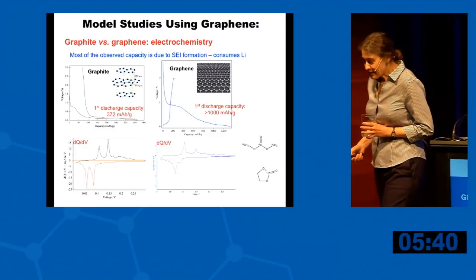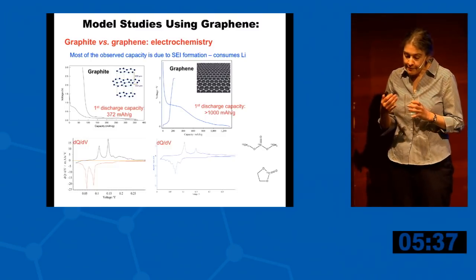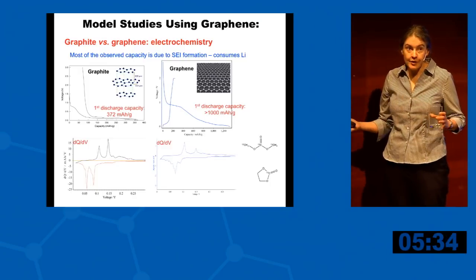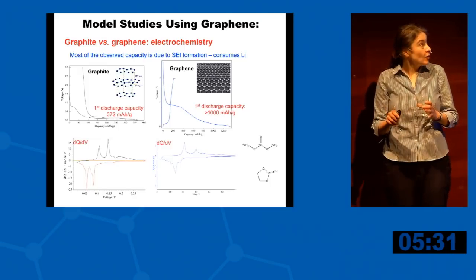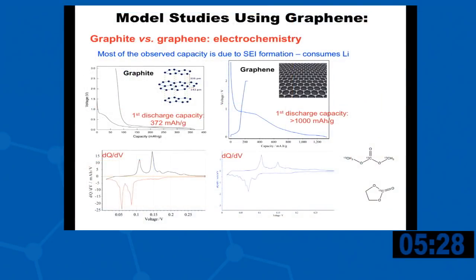So sadly, I didn't spend very much time talking about that. My feeling is that the SEI, for those not in the field, forms because at low voltages the electrolyte will react and decompose, so you have to minimize the surface areas of your structures at low voltages. You can reduce SEI formation by adding additives, as you know, like FEC and VC, but ultimately, I think the role that the carbons play is possibly in stabilizing the surfaces. The problem with silicon is that it expands and contracts, so it's always exposing fresh surfaces. So I think that these carbons will play a role in trying to create more stable structures.